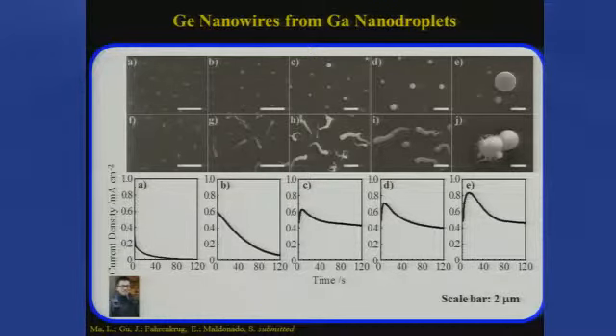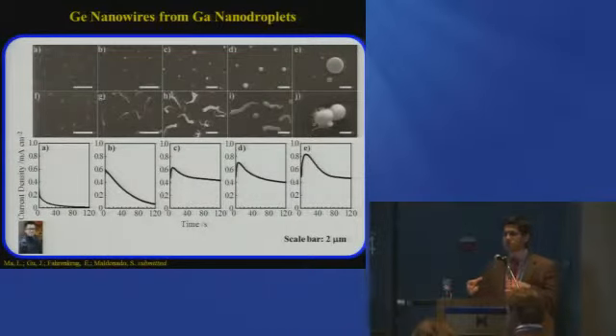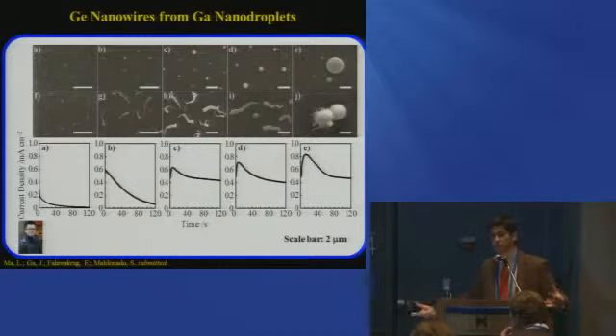These transients change as a function of the pitch and the size. But essentially what we see is that for these larger wires, you eventually reach some sort of steady state growth condition. In this case, it's because you have a bunch of different nano droplets acting like ultramicroelectrodes in an array. But eventually you can reach a point where you're limited by mass transport to the electrode. But I don't yet know whether that causes this particular kink or twist in the crystal that comes out. We're still trying to figure that out, and that's why we want to do those ultramicroelectrode experiments.